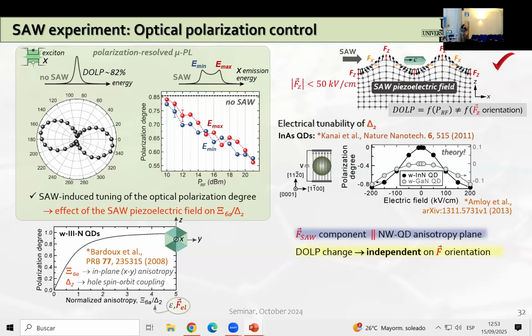Now, it is therefore quite expected that the component of the acoustic piezoelectric field that is parallel to the nanowire quantum dot anisotropy plane, and whose value can reach some few tens of kilovolts per centimeter, can indeed be used to change the photon polarization state. In this case, the change in the degree of linear polarization, as we observe here, is completely independent of the field orientation. What is important is that this field is parallel to the quantum dot anisotropy plane.